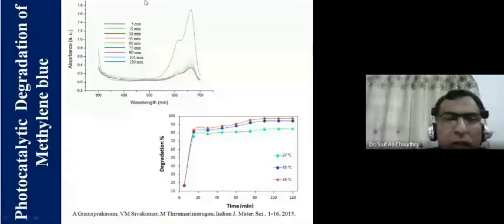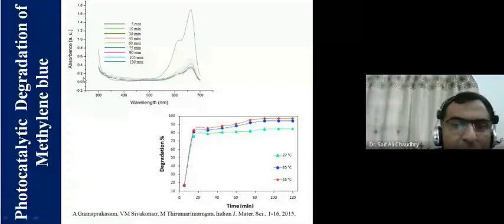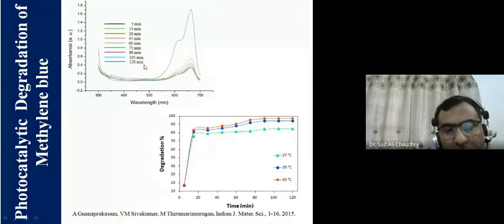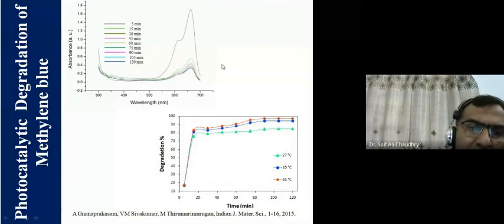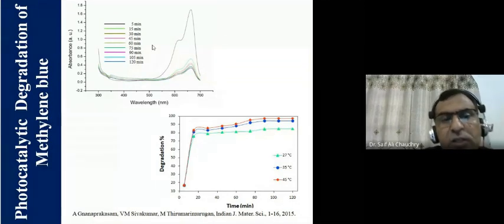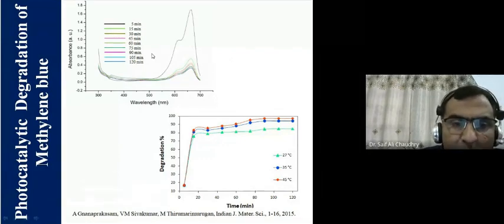Now, the composite was also used for photodegradation of the dye molecules. We started with 5 minutes, 15 minutes, 30 minutes, 45 minutes, 60, and up to 120. You see here the absorbance was maximum. Therefore, the concentration of dye was maximum at 5 minutes, but it reached the minimum value at 120 minutes. So 120 minutes was sufficient time for the photocatalytic degradation of methylene blue from the solution.